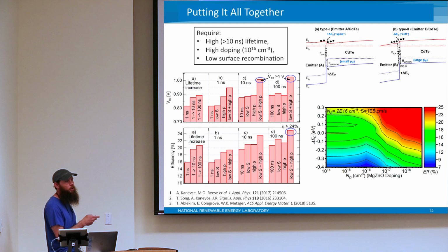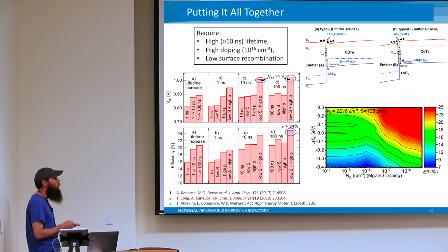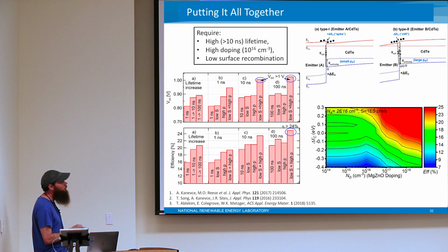So I've only got a couple more slides. Normally in the cadmium sulfide device, you have what's termed a cliff, where you could instead put in a little spike to push things away from recombining right where you don't want them to recombine. By playing games with this, even with a relatively high recombination velocity, you can start getting out into that 25% range and higher voltages.